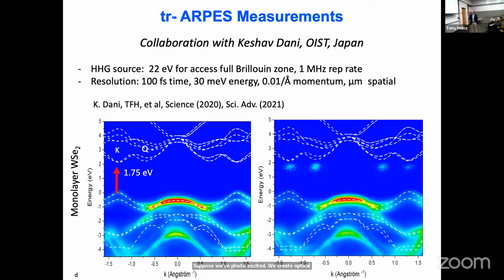Is this symmetric? Oh, there are actually some reasons. So there's slightly different selection rules. I mean, the band structure is selective. The intensities actually do have some inherent asymmetry because you don't have full mirror symmetry in the problem. But mostly it's signal to noise, actually. So you'll see, this was I guess data from 3 years ago, and actually they get more and more symmetric and look nice as we go on. It was, I have to say, a sort of heroic experiment being able to see anything.